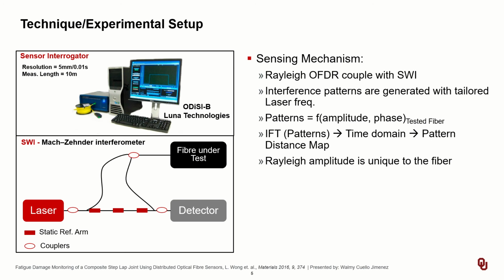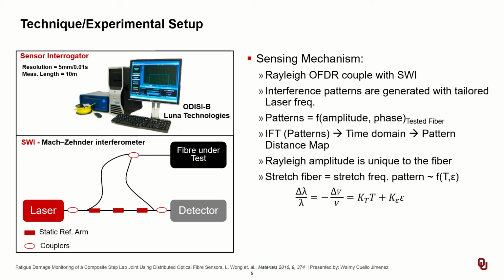It is also important to specify that the Rayleigh amplitude is unique to the fiber being employed. Therefore, as you stretch the fiber, the frequency pattern is also stretched. And as the frequency is proportional to temperature and strain, it is possible to calibrate an optical change, a frequency change and a wavelength change, into a resultant temperature or strain measurement, as the equation below is showing. In this equation, lambda is the wavelength, v is the frequency, k sub T and k sub epsilon are the temperature calibration and strain calibration constants.